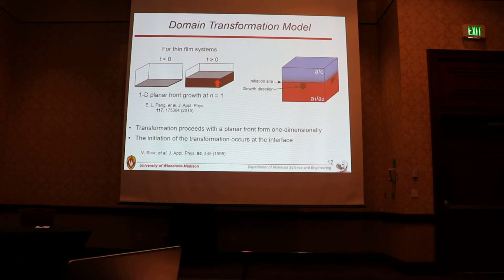So we have the pre-existing nuclei, in this case the AC domain pattern. We can reasonably think that the initiation site is the interface between AC and AA domain patterns, and the growth direction is downward in the form of a one-dimensional planar front. This result is quite interesting because usually phase transitions or domain wall nucleation and growth occur two-dimensionally, not one-dimensionally. So I think there should be some reason why this system prefers one-dimensional growth, not two-dimensional. The theoretical work can help to understand this, but we haven't done it yet.